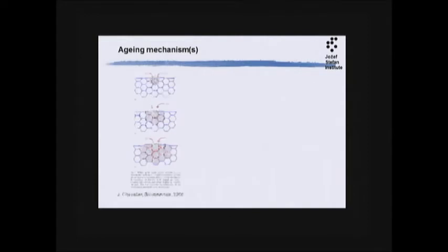Okay, aging mechanism. That's the schematic drawn by Chevalier. Actually, it's not a mechanism, it's just a version of how we figure that out. Somewhere under the influence of water, some grains will decide that they find it uncomfortable in this metastable tetragonal form, and they will start transforming into the monoclinic, and that starts on the surface. Since the volume of the cell is bigger for the monoclinic, you will have here a small uplift, and the material will exert some stresses on the neighboring grains, it makes a loose structure, and that goes deeper and deeper.